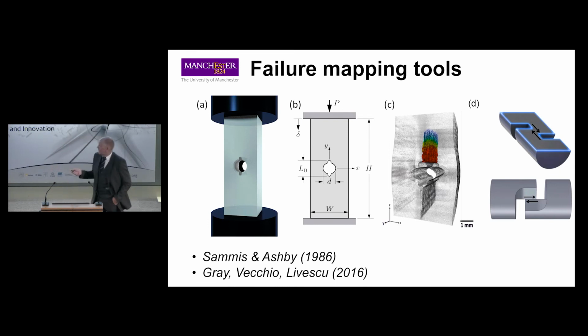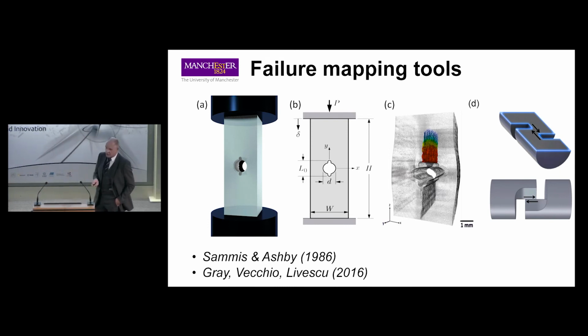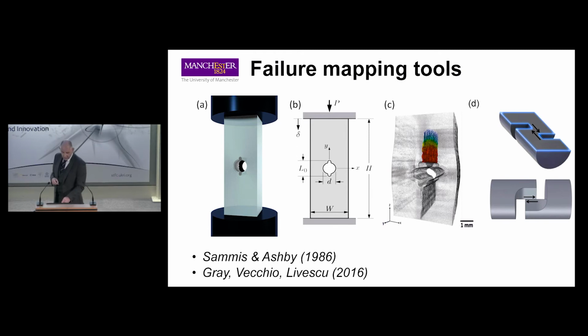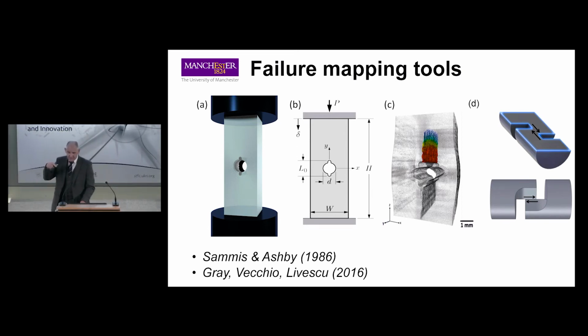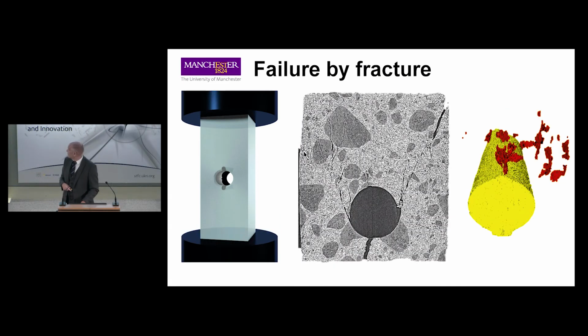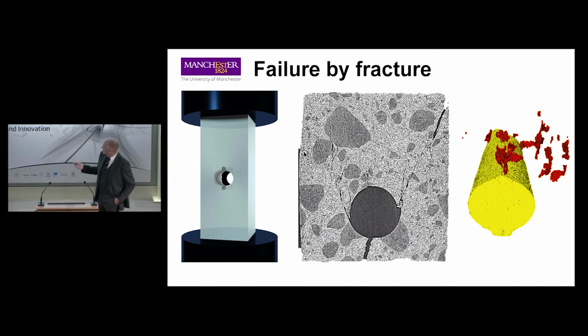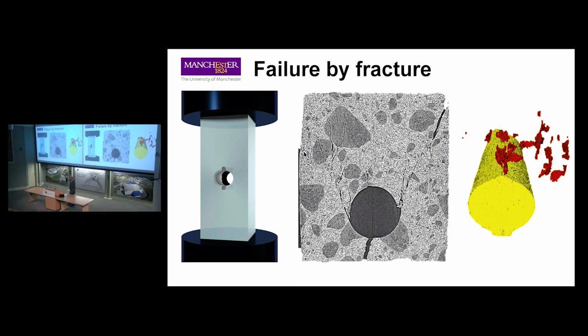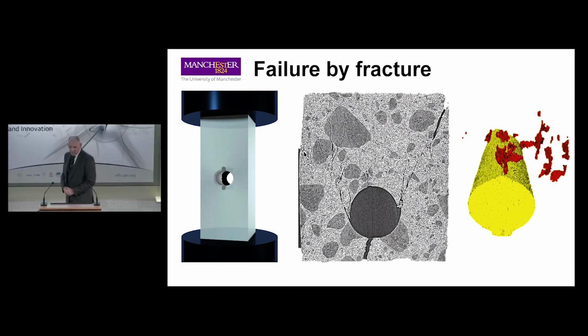This is an example of a series of idealized loading geometries that allow us at one scale to look at failure at the scale beneath. This particular one is for fracture. This particular one is to look at simple shear. And within the limits of the environment that we apply, we can see failure at the scale beneath occurring within those materials. And if one puts in a composite and looks in detail, one can see that a simple crack is, at the scale beneath, in fact, a whole integrated zone full of microscopic failures.